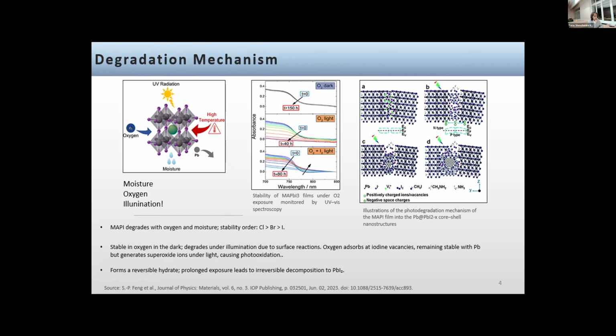And all of these processes are exacerbated when exposed to radiation. And the basic process that happens is that one of the halide anions in the octahedrals detaches and forms a lead iodide molecule, which travels outside of the cell and diffuses in the material. And this makes the whole structure unstable. It leads to the release of the central methylammonium molecule from the structure, which completely disintegrates the molecule further. Right.